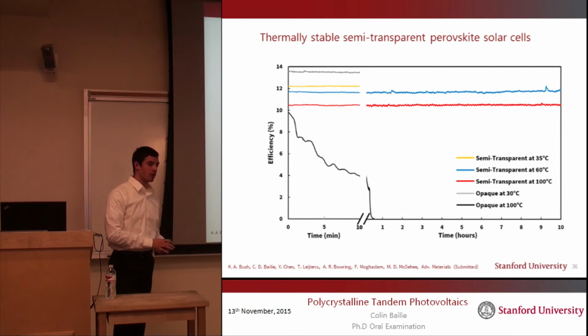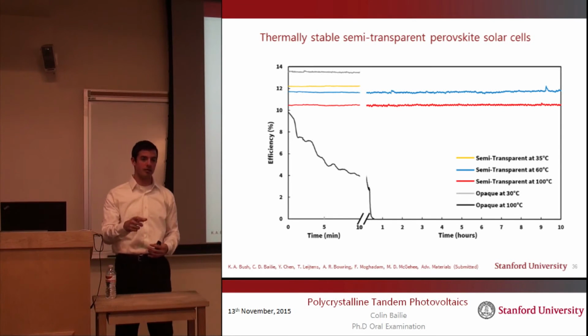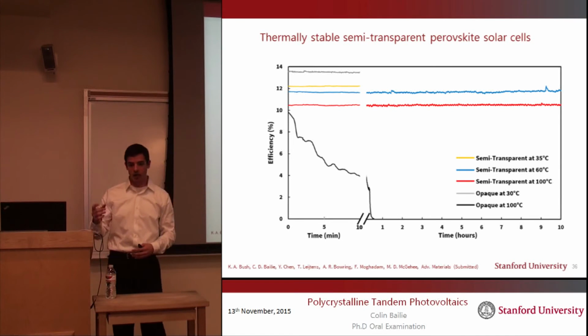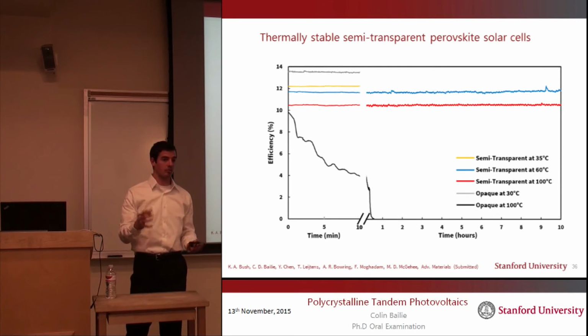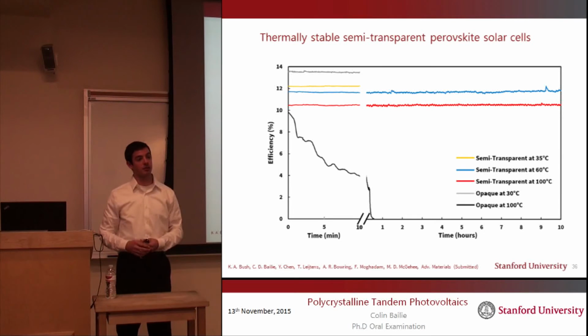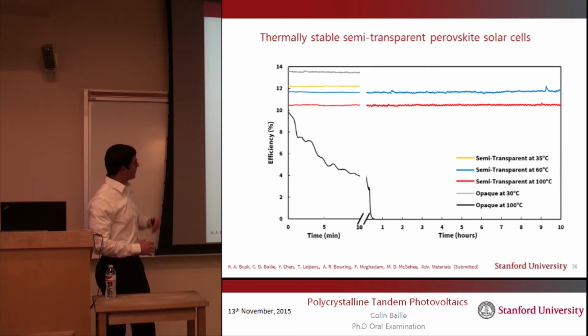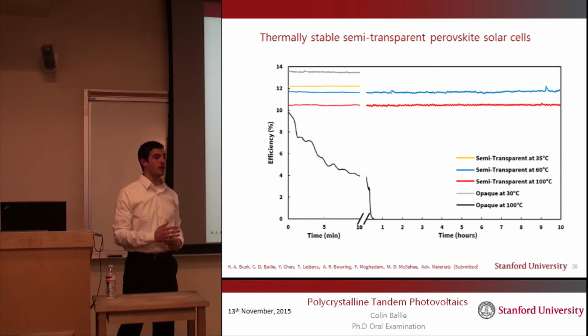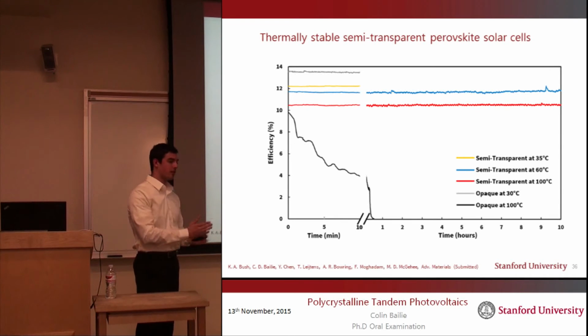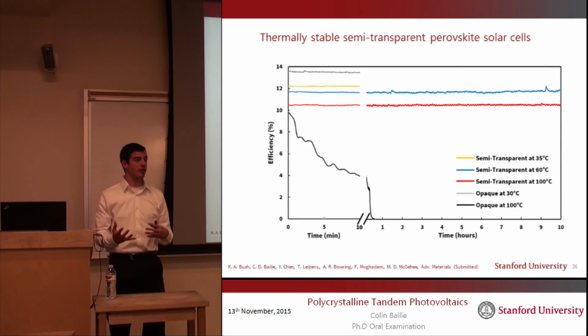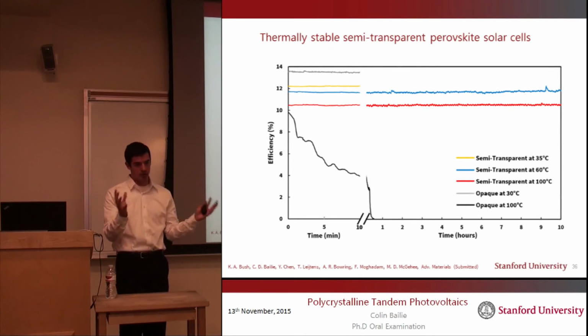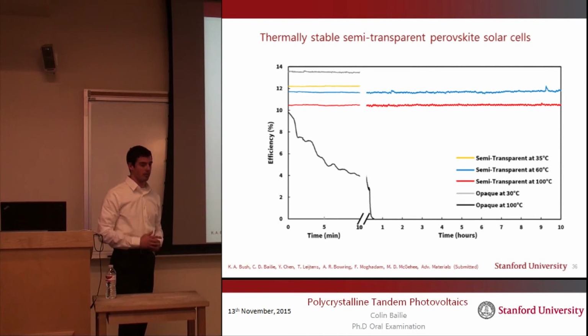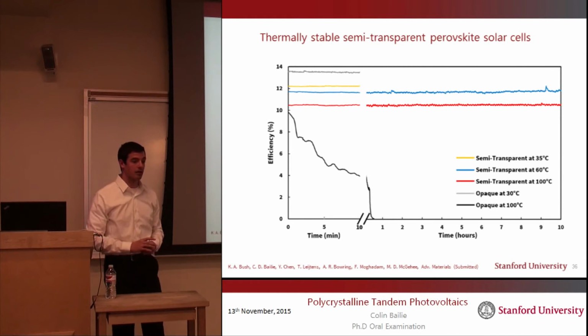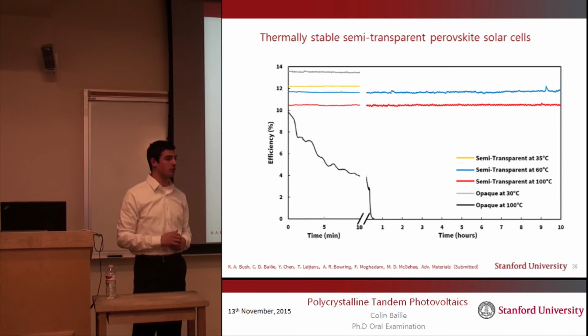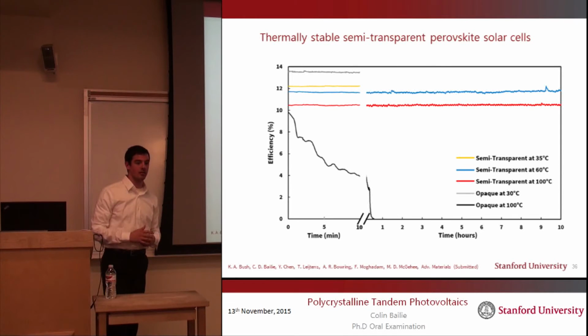And so here is an experiment that we did where we put a perovskite solar cell on a hot plate, and this hot plate was in an ambient environment, so there was moisture in the air. And we illuminated the perovskite with a full spectrum lamp, meaning it had ultraviolet, visible and infrared light illuminating it, and we operated it at its maximum power point over a period of time. And the red curve is the semi-transparent perovskite solar cell being operated at 100 degrees C. And between time 0 and time 10 hours, there was no measurable change as far as we could detect between the performance at those times, meaning that within the bounds of this experiment, we made something that was perfectly stable. This is in contrast to an opaque solar cell in black, which was also at 100 degrees C, and similarly to the video I showed you a few slides ago, it degraded in a matter of minutes and completely stopped operating.